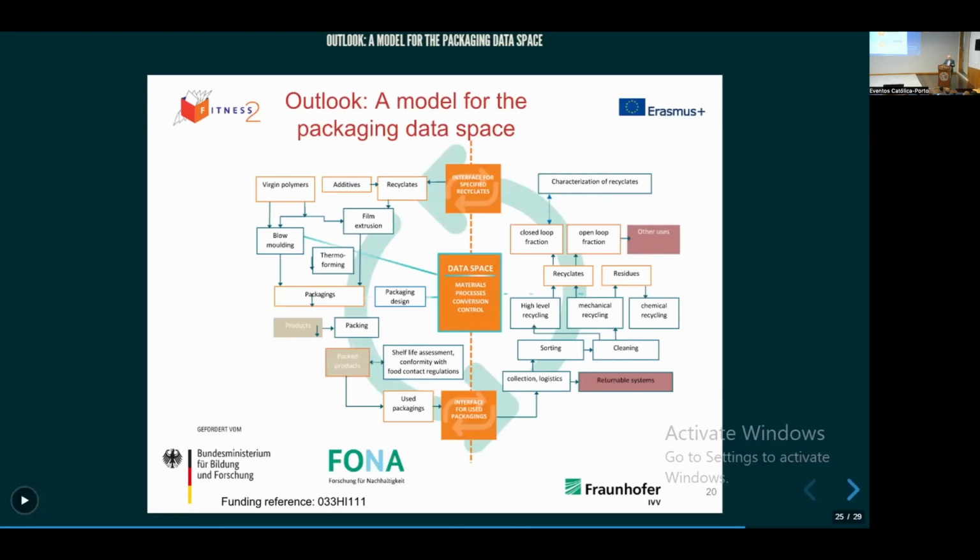The other technique is to coat the inside of containers, be it cups or bottles, for instance. This is something that's already also available on the market, also with a thicker, 80 nanometers. It's still extremely thin, but also there we need thinner layers for economy and also for many other reasons. So the thicker layers can be applied, and you can buy equipment that's able to do it.